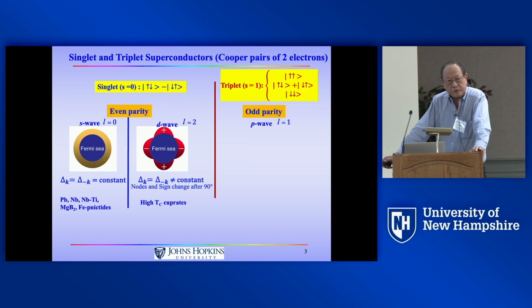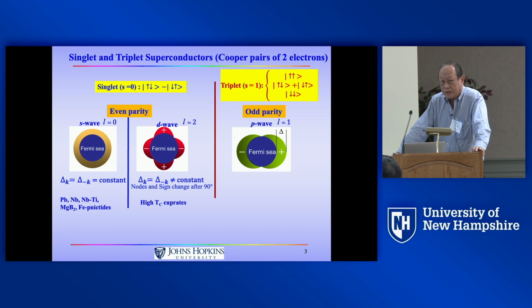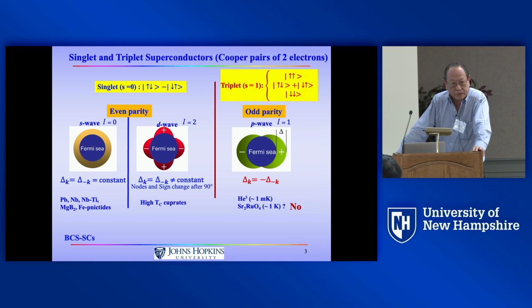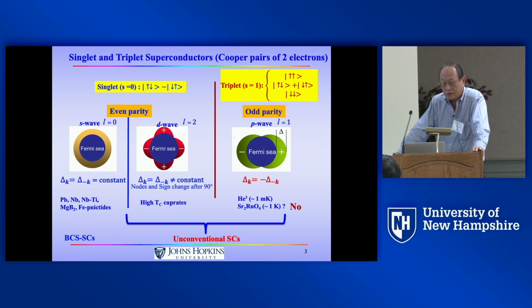Two electrons can also form spin 1. That becomes the triplets, and triplets have odd parity. By that I mean, if you now make an inversion, the gap must change sign with a minus sign. Historically, we know helium-3 is a triplet. It's a superfluid. For many years, people believed strontium ruthenate is a triplet. Unfortunately, that prospect has died recently. So all the superconductors we're familiar with are BCS superconductors, the singlets. Anything that's non-BCS is collectively called unconventional, which includes all the exotic ones, including the triplets. So unconventional does not necessarily mean it's a triplet.